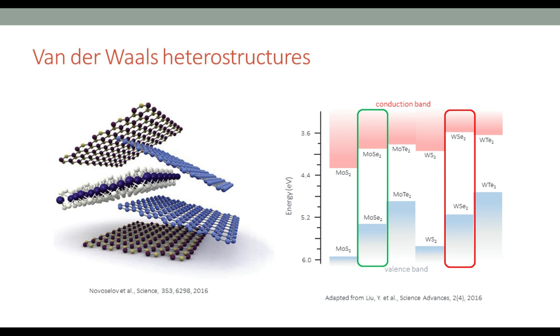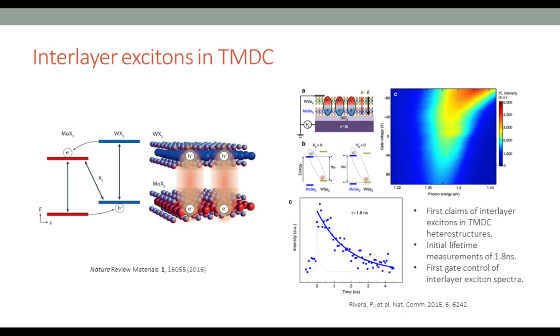So what actually happens when you put them together? Well, first you form a type 2 band alignment, so you can get some sort of PN junction. But also, you can get very interesting excitonic effects when you put the two materials together, one of which is interlayer excitons. The excitons I mentioned before exist in each individual layer, but in this case, since the conduction band and valence band exist in two different layers, the electron and hole are separated in space. They form a permanent dipole moment, and since they're separated, it's more difficult for them to recombine. This is great for a lot of applications because now that their lifetimes are longer, we can manipulate them and do experiments on them.